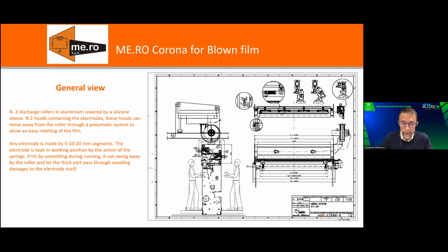So it's very important not to bend the electrode, and we have systems 30 years running that still have the original electrode, straight, perfect, like the first day of the job, because of this characteristic to move away. So this is a very important feature. Another very important feature is the stability of the gap, which means that you don't lose the gap. If with our system you set the gap with the cold machine, once the machine goes in operation under discharge, the temperature of course increases due to the corona discharge, but you have the guarantee that the gap will remain exactly the same.